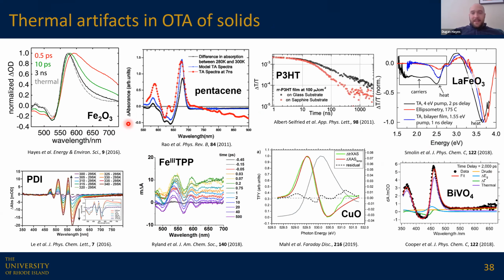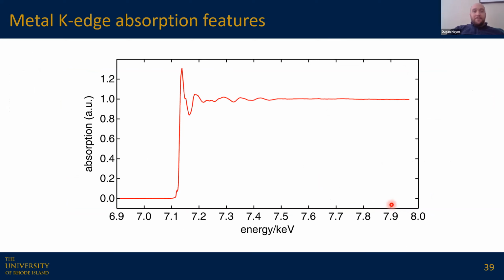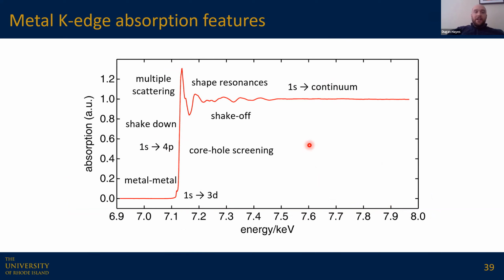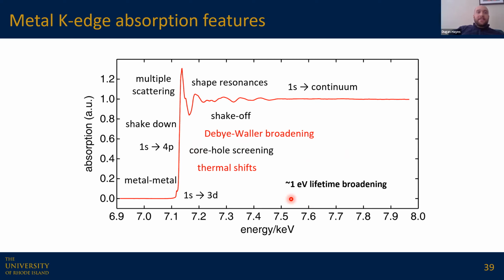And this wasn't new. This has been known for many years, with many examples of different organic and inorganic compounds where optical transient absorption in the solid state is plagued by these thermal artifacts. And in X-ray transient absorption, it's even worse, because we might like to think about a metal K edge as being nicely divisible into the pre-edge, the XANES, and the EXAFS. But in reality, we all know there are many other possible things going on here. We don't really have a good way of modeling this in terms of understanding the core hole screening. We have Debye-Waller broadening that is going to be substantially affected by laser-induced heating. Then we could also have shifts in the spectrum arising from a change in the lattice following lattice expansion when it's heated. And then, of course, this very drastic lifetime broadening that makes everything challenging.